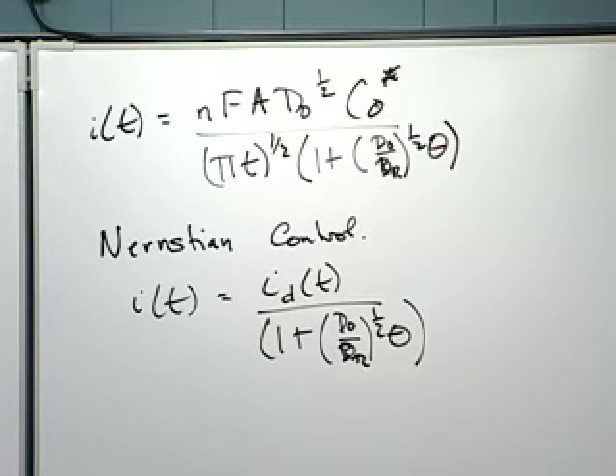And so this would just be adding inaccuracy to the system. So although in theory I could get it that way, experimentally it doesn't make a lot of sense. In addition, what you're going to have to do to use this equation experimentally is make the assumption that D_ox and D_red are approximately the same. In general, a good assumption, but not always, and so that gives you another opportunity to mess up. You'll notice, by the way, since in this particular equation they go as the square root, if you're a little bit off there, it sort of evens out for you. So the math helps you out a little bit there. Okay, so those are the pluses.